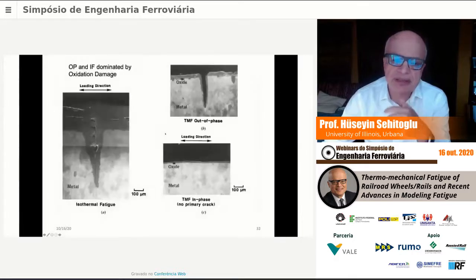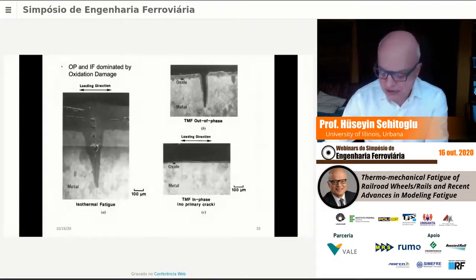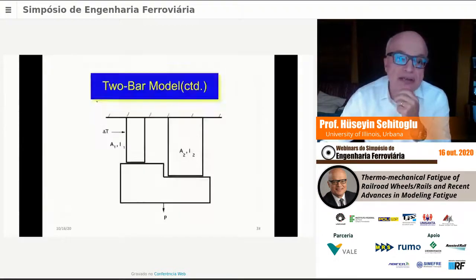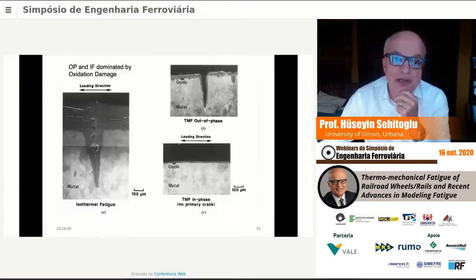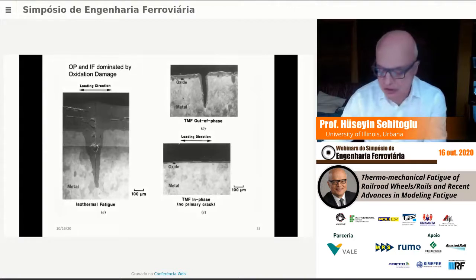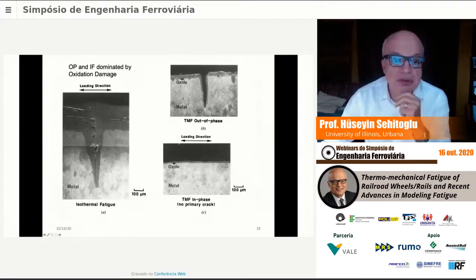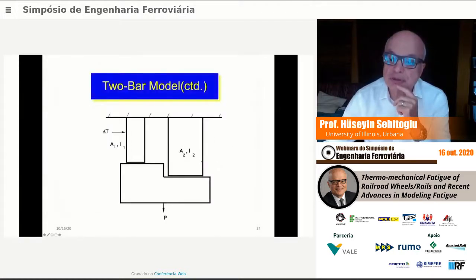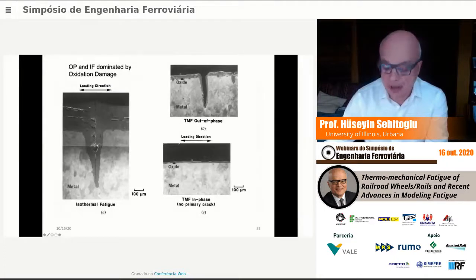It's similar to the damage you get in a creep test. On the other hand, in the out-of-phase case, it's dominated by oxidation damage. Here you can see in the out-of-phase case, you have these oxide spikes that go into the material. Basically, in the out-of-phase case, you get considerable oxidation damage, and in the in-phase case, you don't get much oxidation damage.